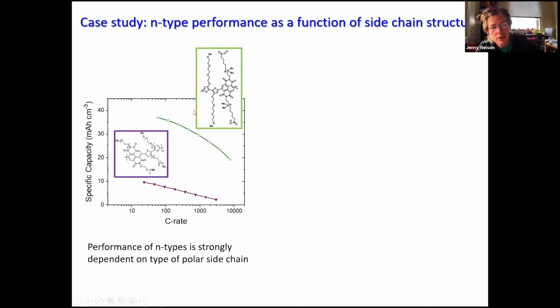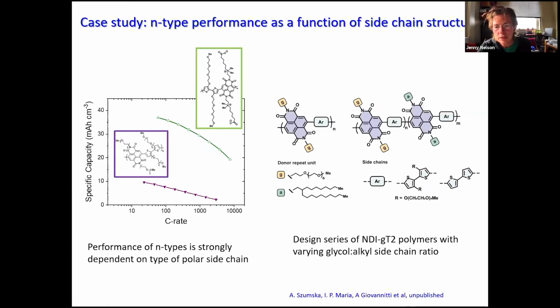And I would remind you of this observation that when we were looking at the rate capabilities of our n-types, we found that replacing a zwitterion with a glycol side chain caused a loss in capacity of about a factor of 3. So it looked as though, although the polymer in some sense is exactly the same, the side chain is very important. And we decided to look at this in a bit more detail by designing a series of polymers which have the same backbone, but the side chains are varied.